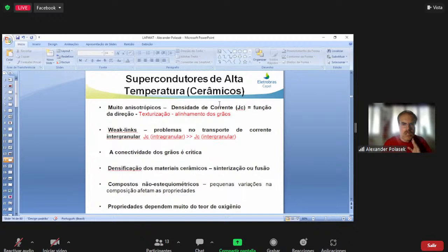However, as I told you, these high temperature superconductors are very anisotropic, and the current density is a function of the direction. You will need to align, the texturization of the material. You have the weak links. Nowadays, in the second generation tapes, this problem has been overcome, but the weak links used to be a big problem in high temperature superconductors, and nowadays it has been mitigated. It's the problem that the intergranular critical current is much lower than the intragranular critical current. So we need high connectivity and densification of the material.